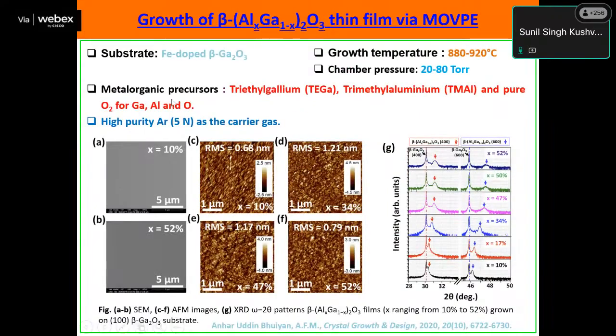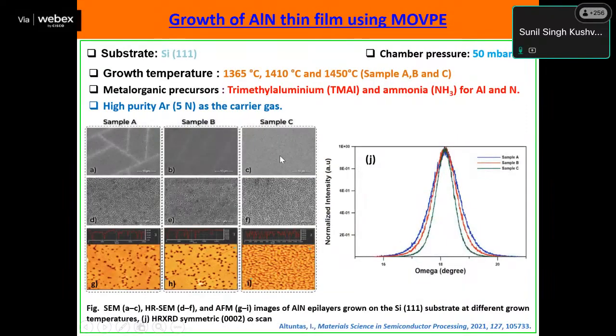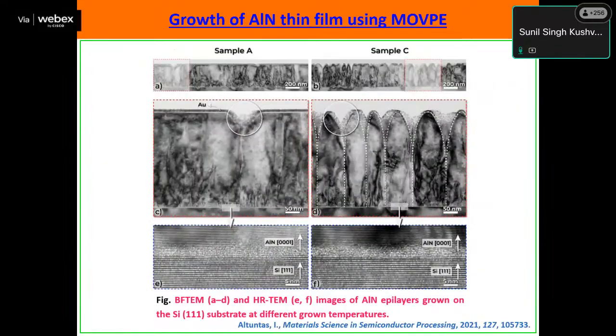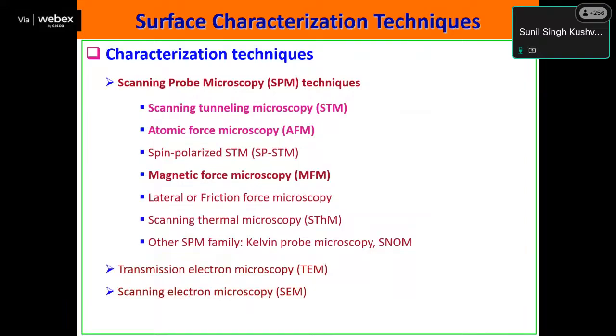And then they even do doping of aluminum in the gallium oxide using this MOVPE. And then some aluminum nitride thin film, as I mentioned, we can grow aluminum nitride using trimethyl aluminum and ammonia as precursors. And then we are even able to get a very low rocking curve width, which shows the high quality of the film.